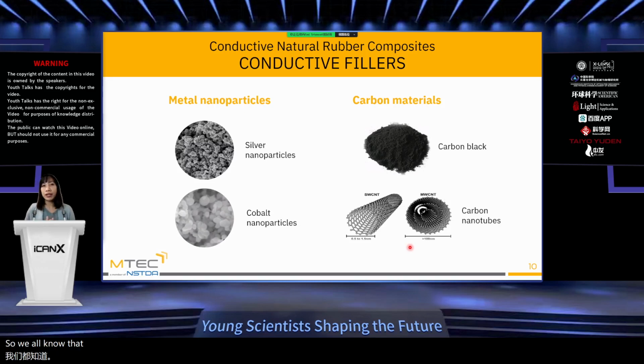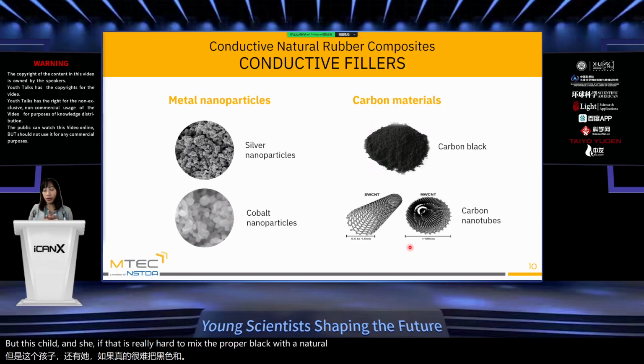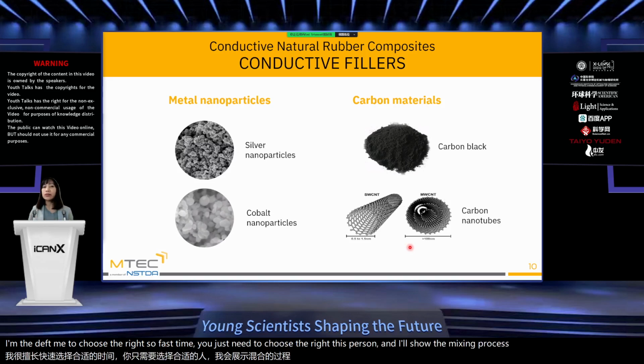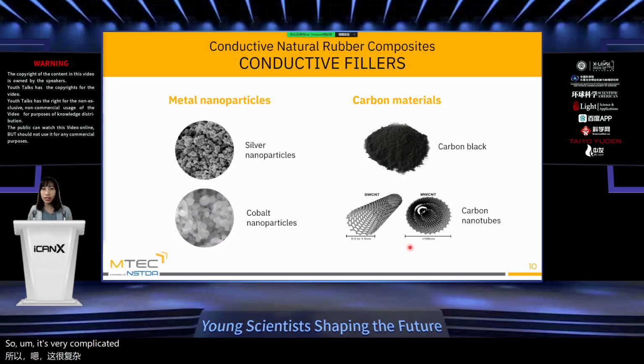So we all know that natural rubber latex is very cheap, but we want to make a profit for the domestic product, right? So I think we should go with something on the cheaper end. So that's carbon black. But the challenge is that it's really hard to mix the carbon black with the natural rubber latex because it is water based. And if you have been exposed to carbon black before, it's oil based. So these different polarities make it really hard to mix together. You just need to choose the right surfactants, the right dispersant, and also the mixing process. So it's really complicated and challenging.